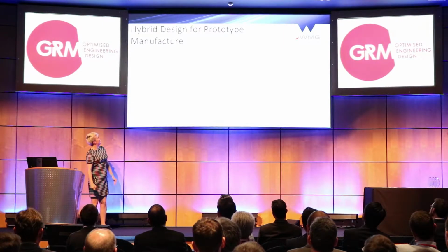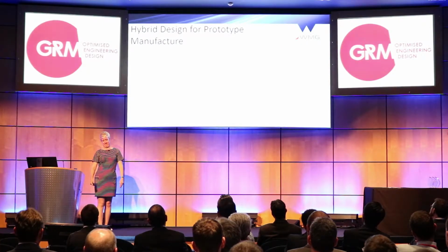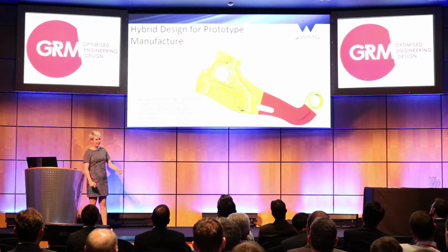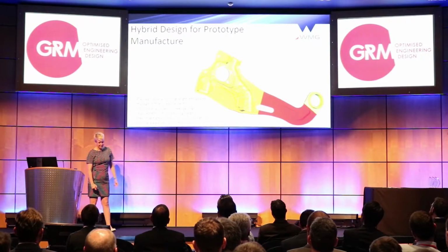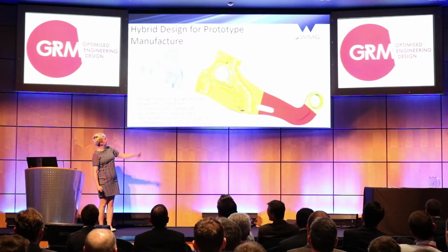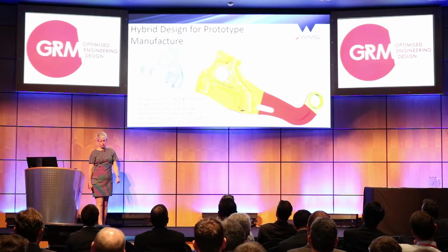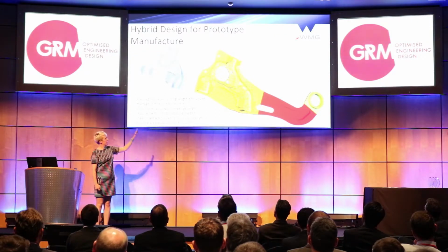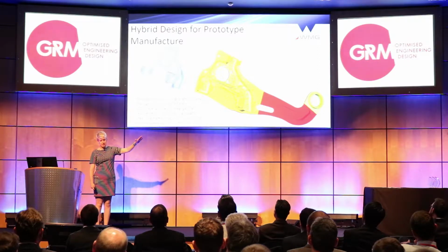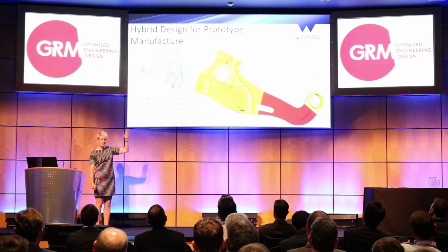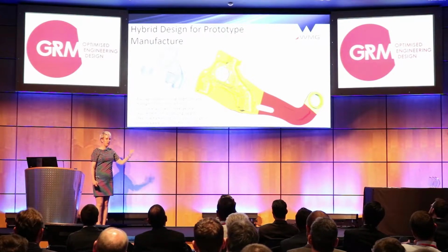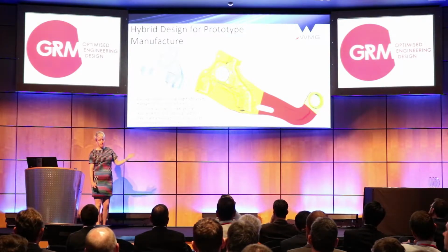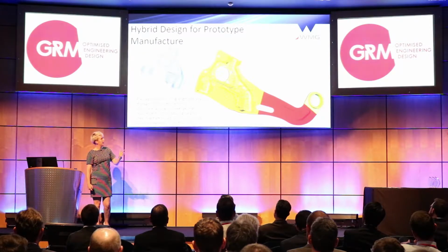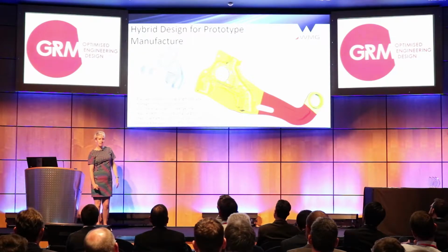So we made it even more complex and even more hybrid, and we came up with pre-preg and SMC and steel. So the steel is this kind of honeycomb structure you can see in the middle. You've got the pre-preg running the length to manage the stiffness, the SMC coming out to meet the clevises, that gets your geometry requirements. Both of those reduce the weight significantly, and then the steel increases the strength in that knuckle area where the SMC is a weaker material.